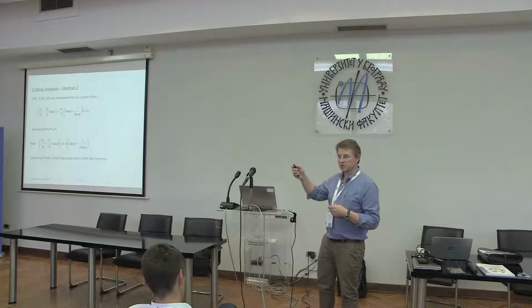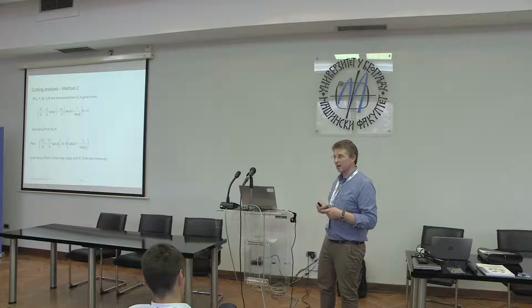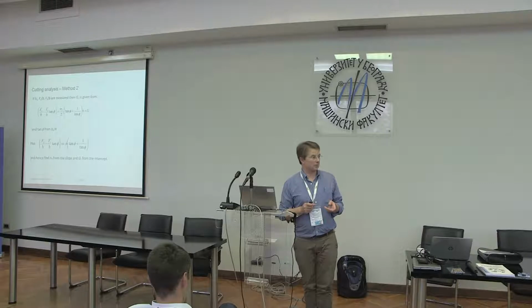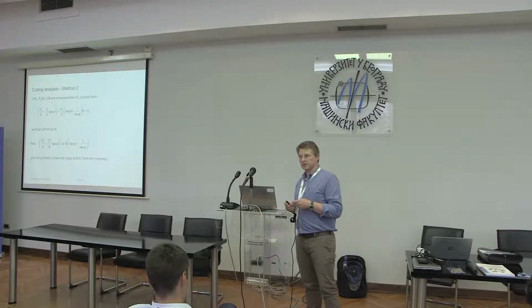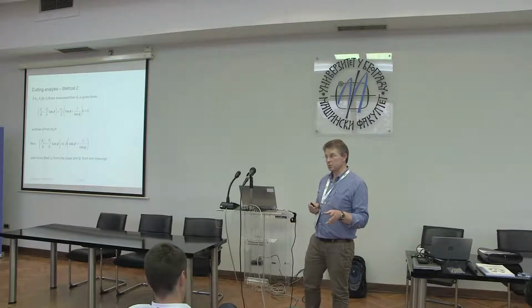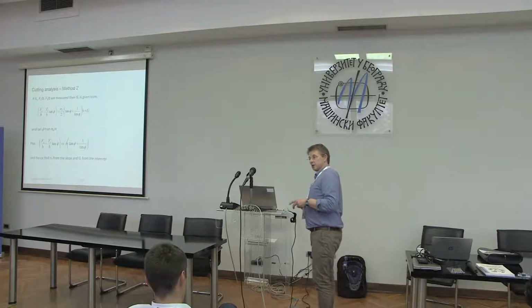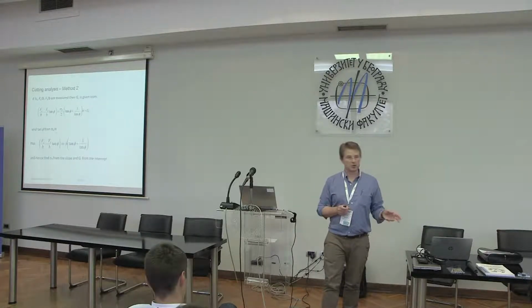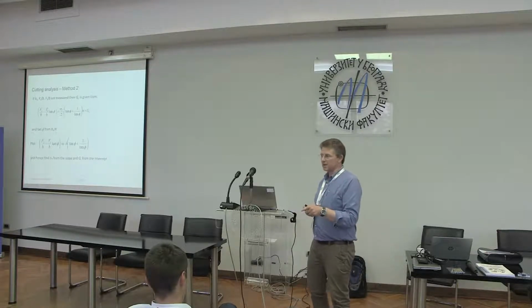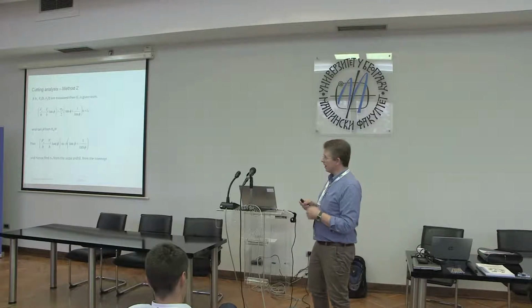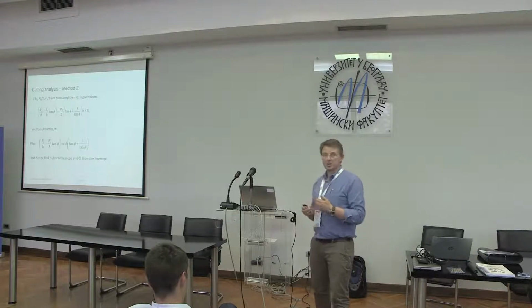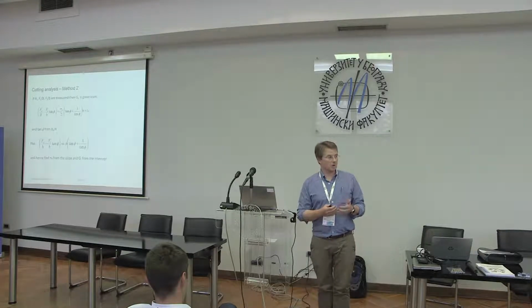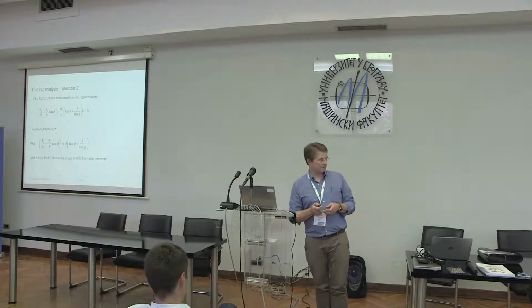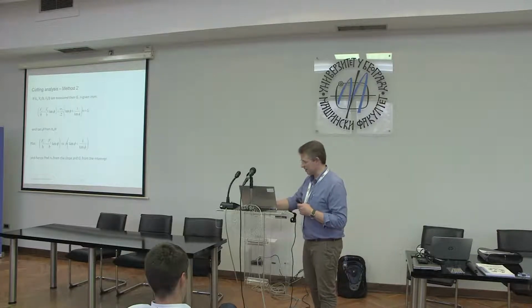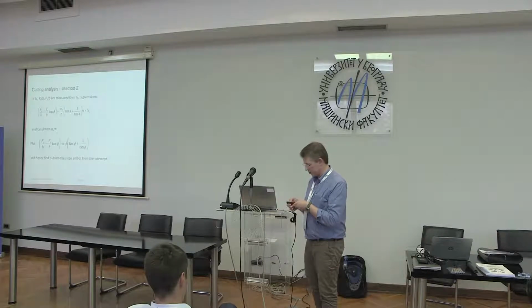So the intercept gives us GC, and the slope gives us a term from which we can determine the yield stress of the material. And what we always found for this polymer cutting work was that the yield stresses were high relative to the uniaxial yield stresses that we would measure in a separate test. So we surmised from that that, obviously the deformations are large, so we had a large amount of work or strain hardening in this material. So we rationalised the relatively high values of yield stress in those terms.